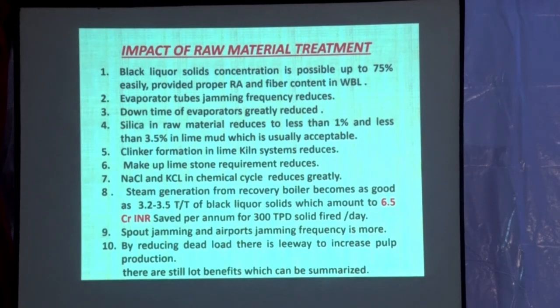But I am quite agree with Dixit ji, because it is just the boundary line. If you reduce the furnace oil to get more purity, instead of increasing it will decrease, because the silica will bind with the calcium oxide and form calcium silicate, and you will find in your test result that we are giving more fuel but purity is getting down. So lesser the silica, better purity of the lime. I am quite in accordance with Mr. Dixit. So then clinker formation in the lime kiln will reduce.